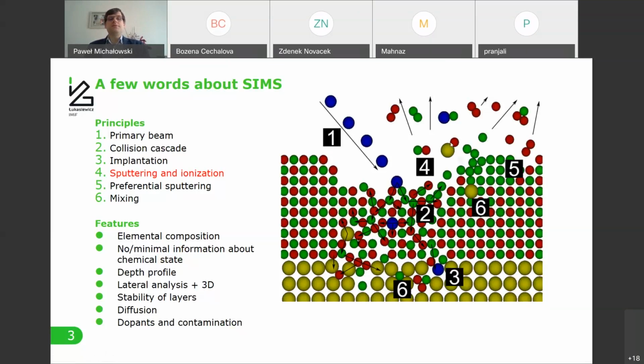So usually this is used to detect some kind of stability of layers, where there are sharp interfaces, or there is some kind of mixing of these layers. Of course, the diffusion phenomenon is very well detected. And due to the excellent detection limits of the SIMS technique, it's commonly used for dopant and contamination analysis. And what I would like to mark here is that typically it's not used for 2D materials. There are not so many publications that show such applications due to the thickness of these samples. But with some enhancements, it can be done with a very high precision.